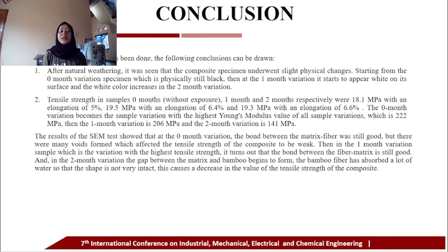The results of the SEM test show that at the no exposure variation, the bond between the matrix and fiber was still good, but there were many voids formed which affected the tensile strength of the composite to be weak. Then in the 1-month variation sample, which is the variation with the highest tensile strength, the bond between the fiber and matrix is still good, and in the 2-month variation, the gap between the matrix and bamboo begins to form. The bamboo fiber has absorbed a lot of water so that the shape isn't very intact. This causes a decrease in the value of the tensile strength of the composite.